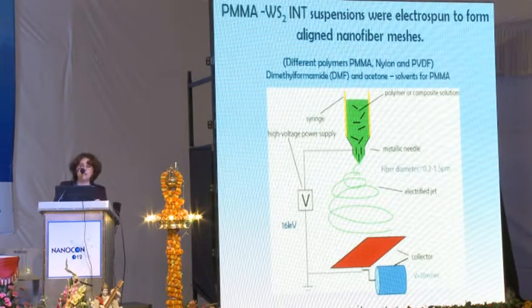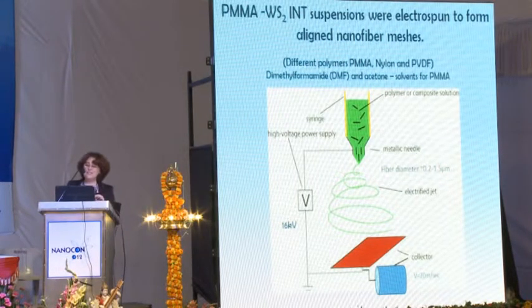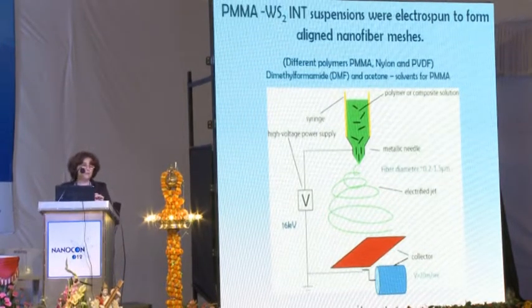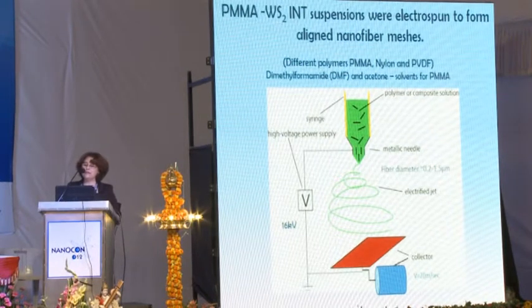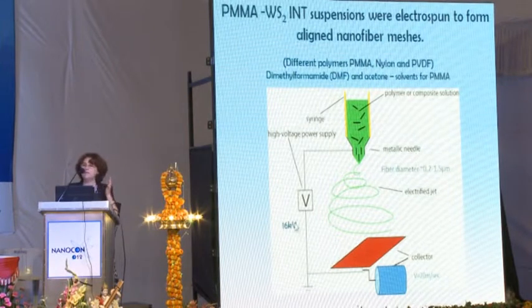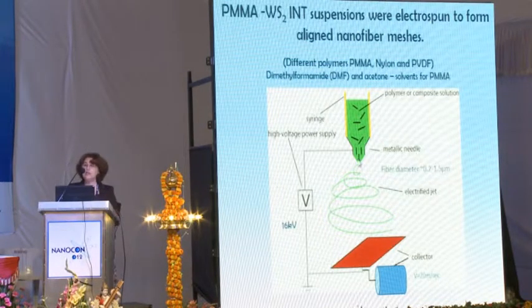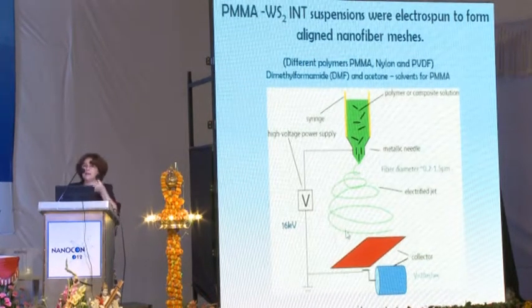One of the applications of this material, which I can touch on in these few minutes, is the preparation of nanofibers from polymer. The method applied to prepare these nanofibers is so-called electrospinning. You have a solution of polymer, and you put dispersed nanoparticles into the solution. The solution has a very small viscosity, so it can go through the nozzle of a syringe, and under a very big electrical field of 16 kilovolts, or depending on the solvent up to 30 kilovolts, you pull this drop and create very long and thin nanofibers of polymer.